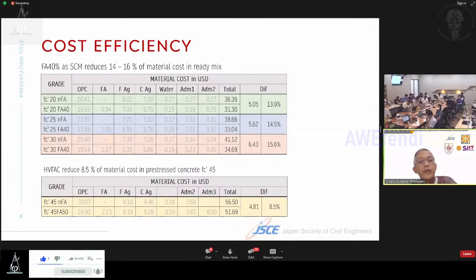And for FC 25, we can save 5.62 US dollars per cubic meter, or about 14.5% of the material cost. And then for FC 30, if you compare non-fly-ash with fly ash 40%, we can reduce the cost by about 6.43 US dollars, or about 15.6% of the material cost.